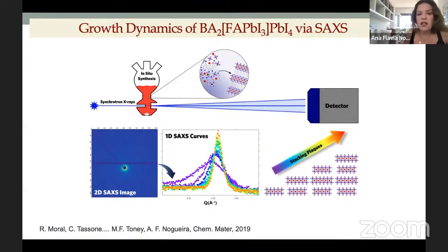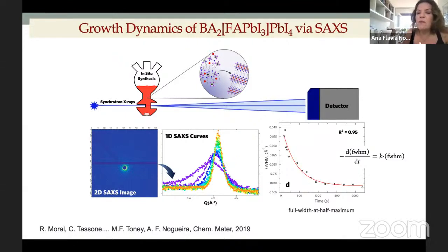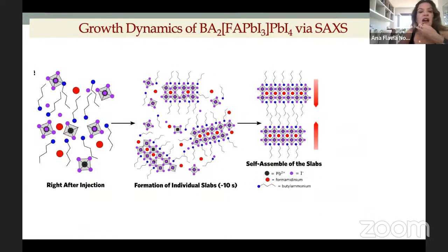So you can see here in the beginning, you just see a broad signal. As we start to see the formation of 2D, we can follow this signal here. It starts to become narrow and more intense. This is interesting, because we are doing these experiments with time. So that means that you can do some kinetics here using these in situ experiments. And with that, we were able to see what was going on here.